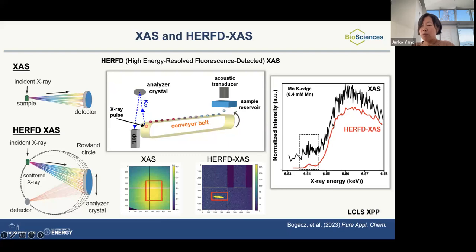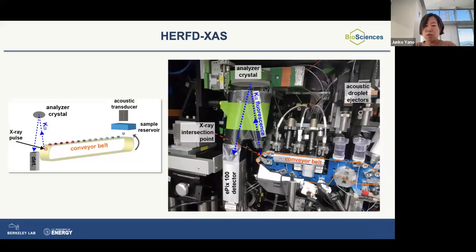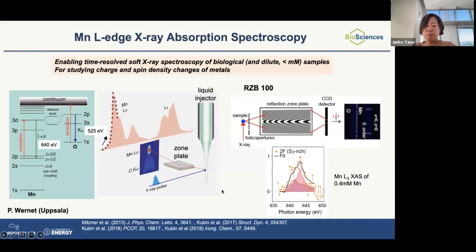That way, we could collect the HERFD-XAS like this, and as you can see, the quality is much, much better, and the data collection time is much faster as well. So that's what we are trying to do, and this is the actual setup. You can see the analyzer crystal here, the detector down here. So that was the manganese K-edge side of the experiment.